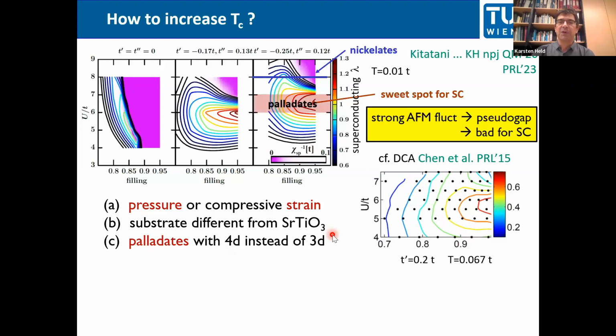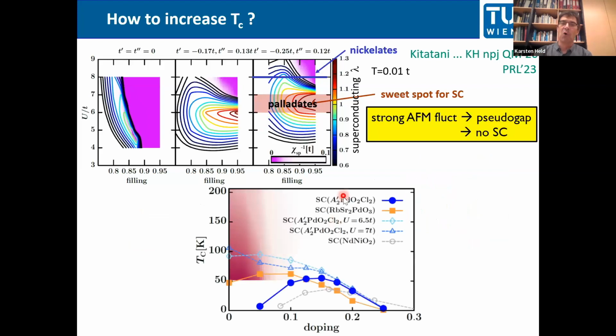Now let's first start with the palladates. So our hope was to go with the palladates into this sweet spot region, and we also managed to do so. It turned out to be more complicated than we thought at the beginning. If you just take lanthanum, palladium, O2, it goes down to too small U values. But if you have a more complicated palladate, like here in blue and orange, you hit the best region, and that increases the TC quite substantially.